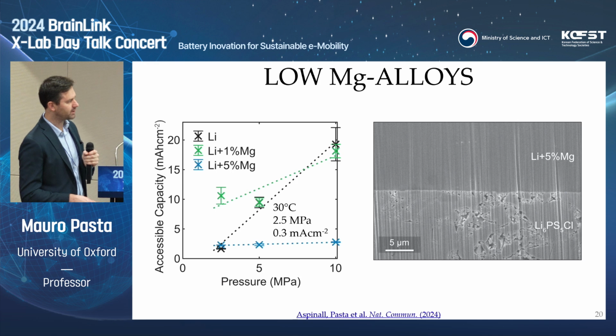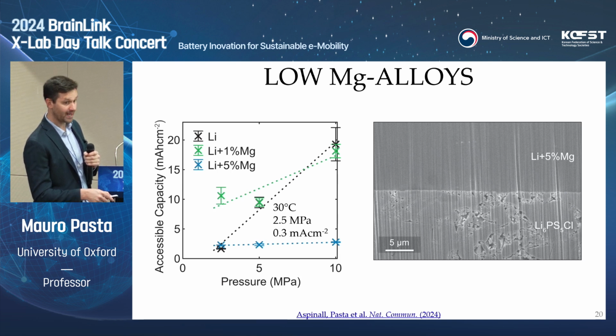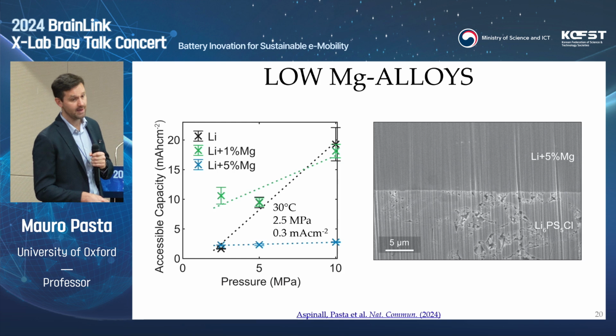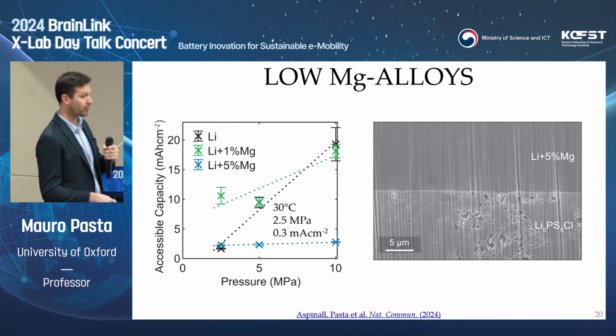So now the fundamental problem here, if you look on the left-hand side, is to find a good compromise. If you see the curve, the line in black here, that's pure lithium. As you increase the pressure, you can rely on yielding and creep, and therefore increase accessible capacity. So at high pressures, you get a lot of capacity out of your lithium, but it's a function of pressure. And at low pressures, the accessible capacity is quite low. The 5% magnesium in blue here, as you can see, you retain pretty much the same accessible capacity, so it's almost pressure independent, but at the same time, the accessible capacity that you get is not particularly high, and that's due to the fact that even 5% compromises diffusivity enough to then slow down your transport.